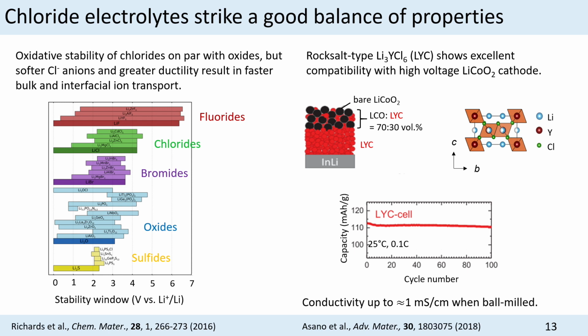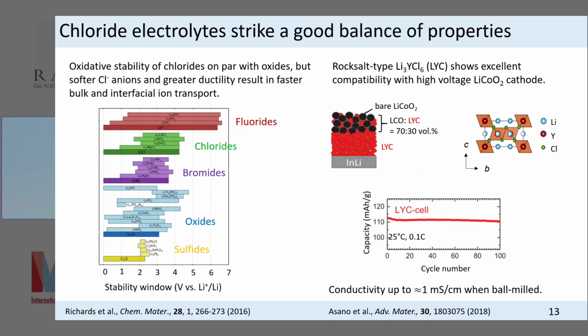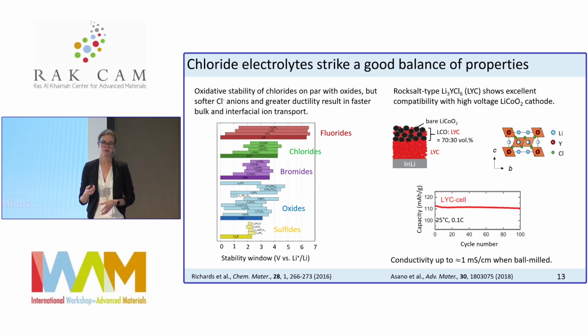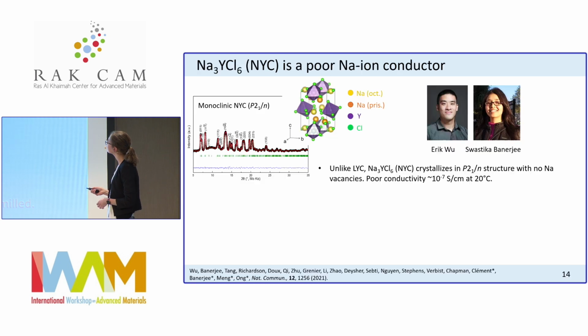So there was a revival of interest since this particular study of lithium yttrium chloride, or LYC. I'll call it LYC today. This is work by a group at Panasonic in 2018 that showed that this LYC system, if you make an all-solid-state battery out of it and you cycle it against a high-voltage lithium-ion cathode, you'll get a very stable performance for 100 cycles. And you also get a high ionic conductivity with this material, of 1 millisiemens per centimeter, so on par with what you would get for a liquid electrolyte.